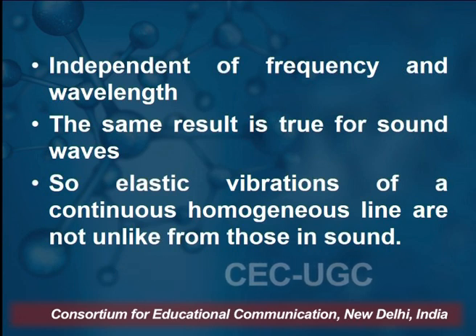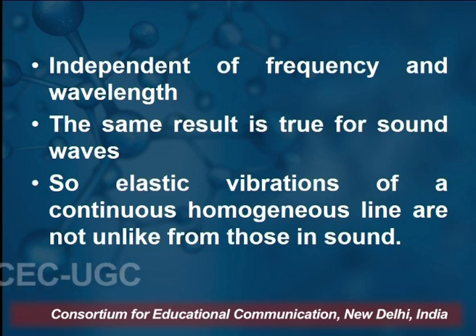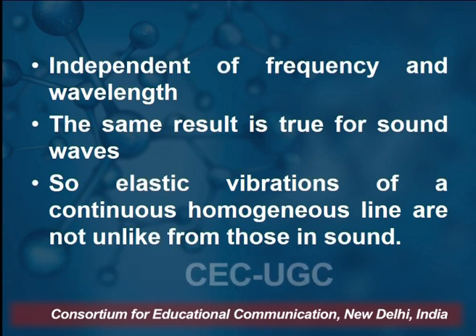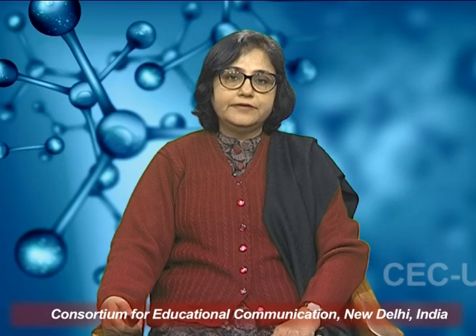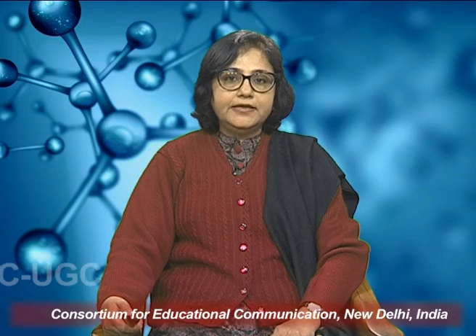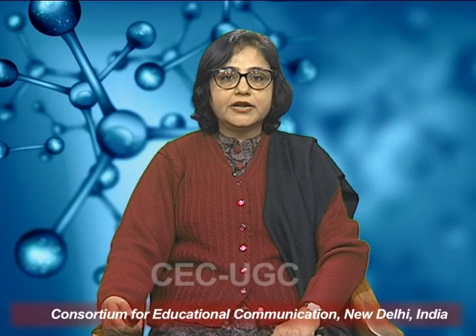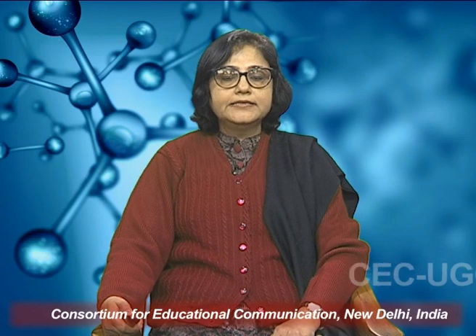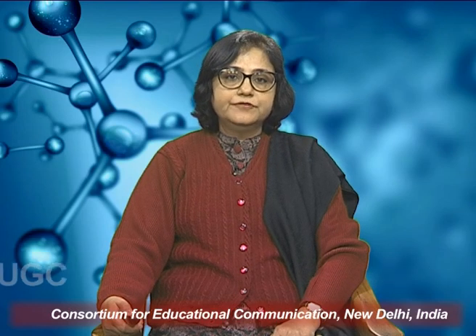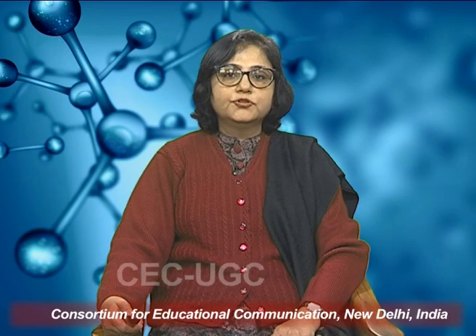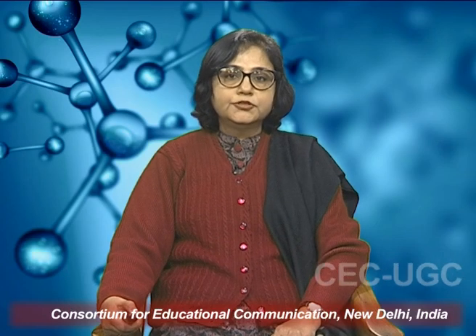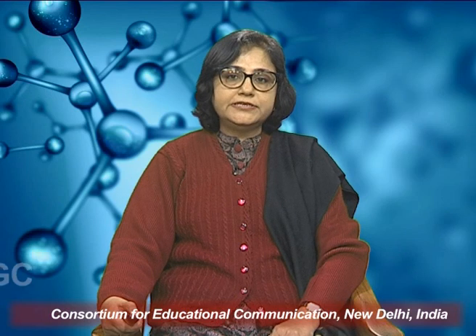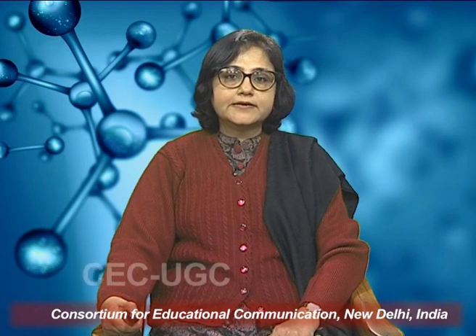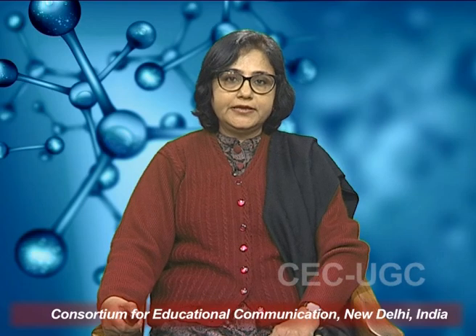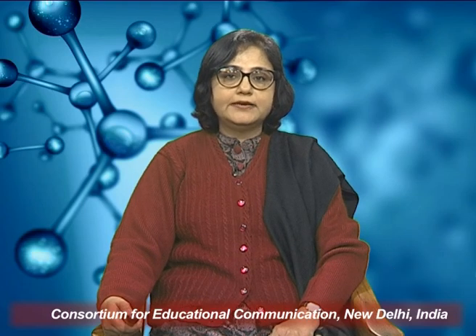In this case, both Vp and Vg are independent of frequency and wavelength, and the same is the case for sound waves. This means that the wave propagating as the elastic vibration of a continuous homogeneous line is the same as that of sound waves, which means that the wave propagating through the homogeneous isotropic line is a sound wave.